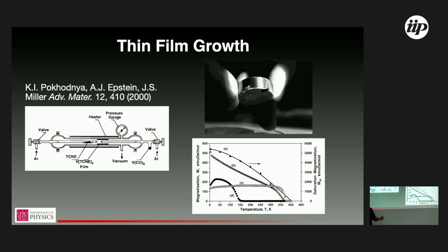I mentioned the deposition temperature is about 60 degrees Celsius, and just generally from a materials perspective, that tells you about how hot a material can be before it starts to decompose. So you'll notice that's suspiciously close to the transition temperature here, and the shape of this curve doesn't really look like a magnetic transition. I have a long-running debate with Joel Miller about this, but I would say this is a structural decomposition, if you want to call that a magnetic transition when you vaporize your sample. That's fine. It's phenomenologically the critical temperature.